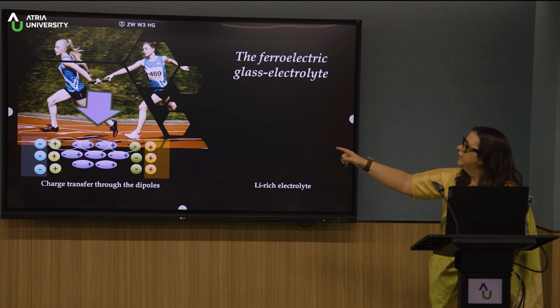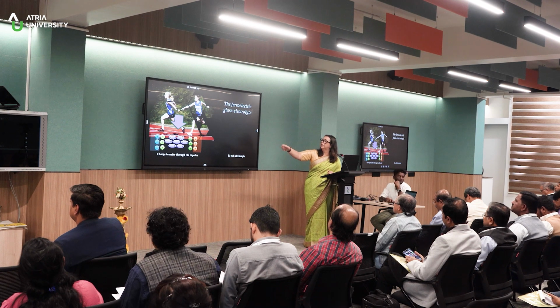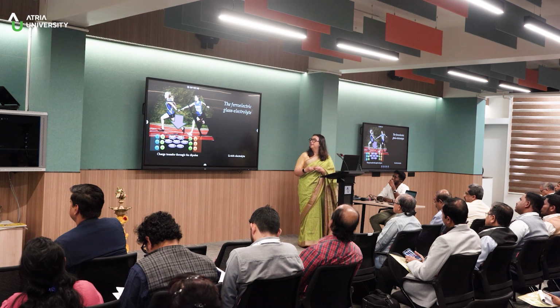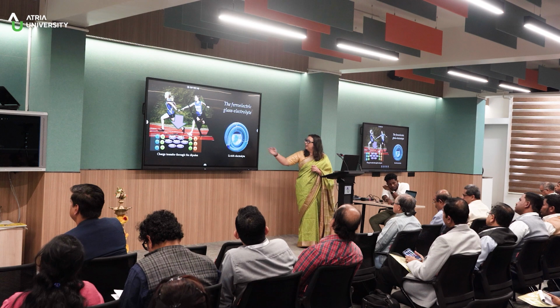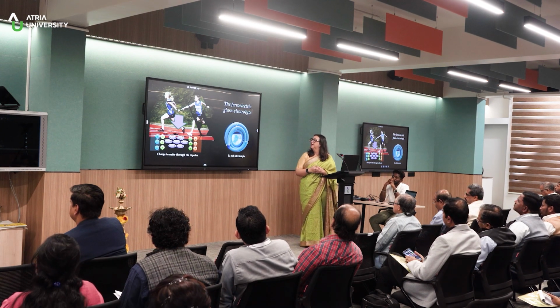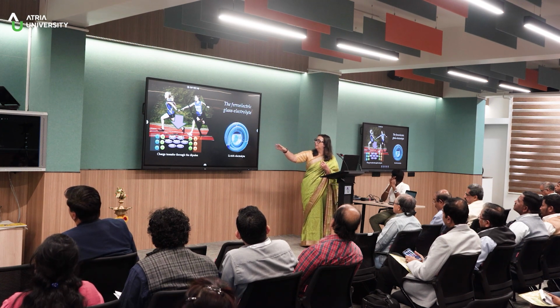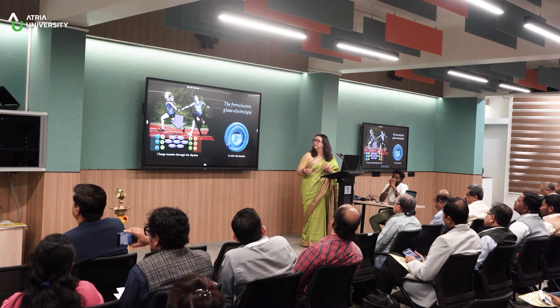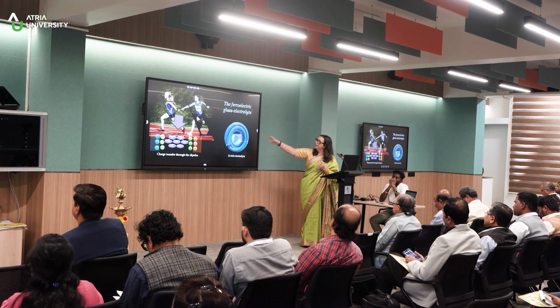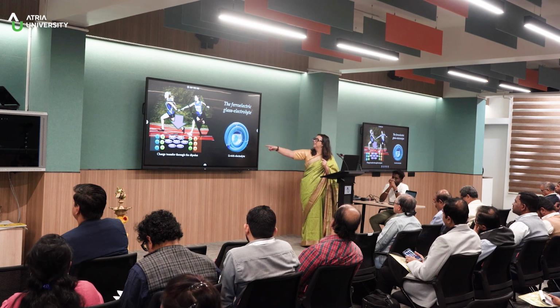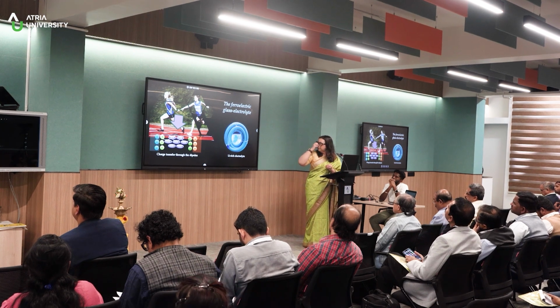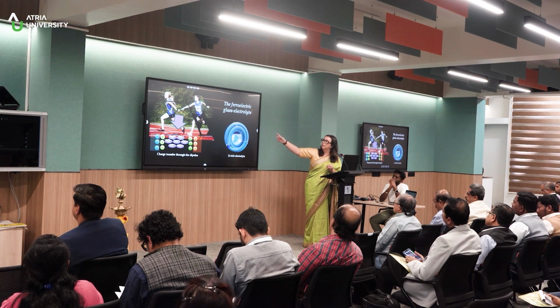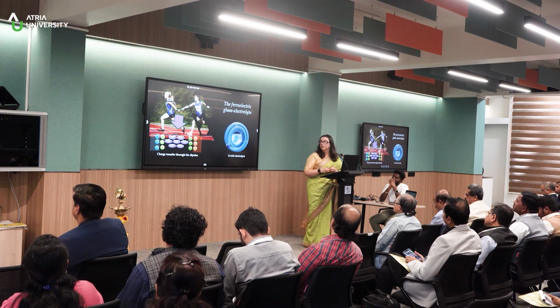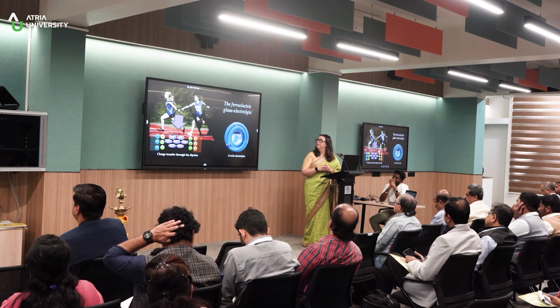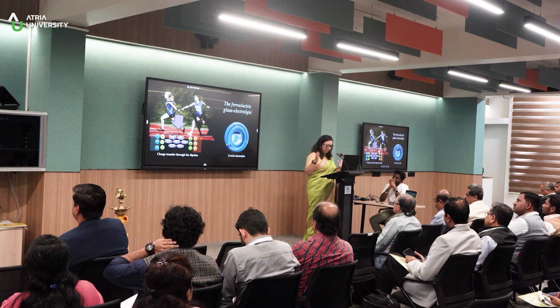If you have dipoles, then the displacement of the ions will be much smaller, because you can use one end and then you shift the polarization. So this is how it works, and then you gain energy there. And if you have a very lithium-rich electrolyte or sodium-rich, then this is much easier, because you have sodium or lithium all around. Each of the ions only has to displace a little bit. It's like having a big hose where you already have a lot of water, or in this case, a lot of ions. So when you turn on the tap, the first water that comes out is the one that is already in the tap, in the hose. So you really don't have to displace the ions much for having the supply of ions on the electrode side.